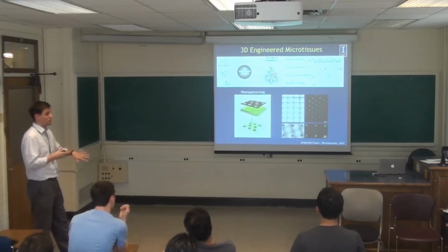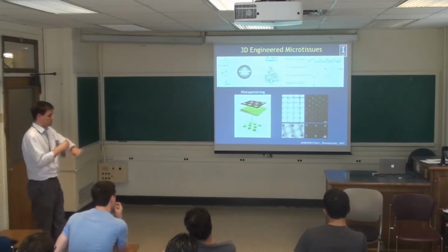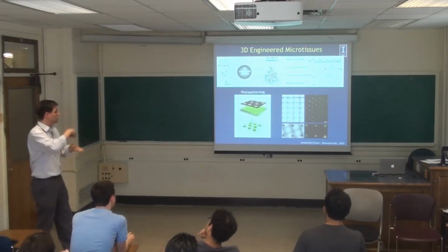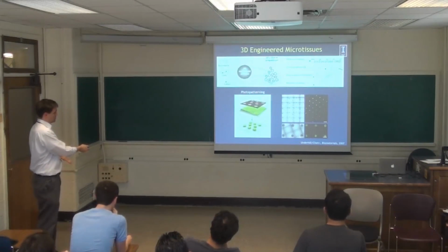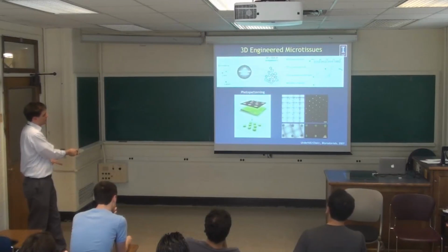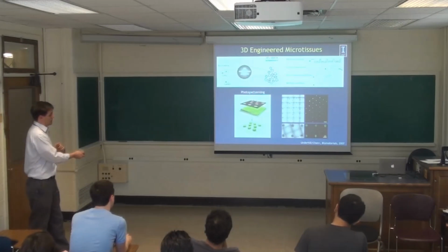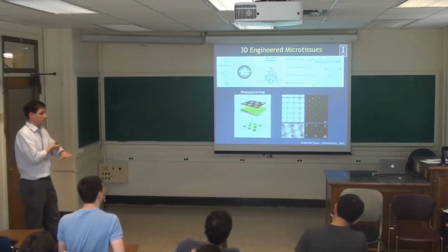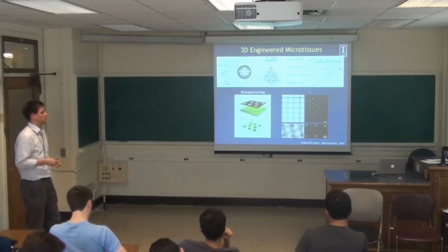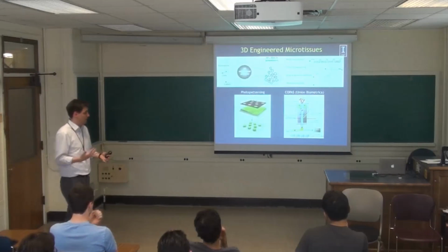One way that we used in some of our initial experiments was essentially photopatterning. So essentially, if you have your pre-polymer solution with cells and then you expose it to UV through a mask, illustrated here, then you essentially will have these microscale domains that polymerize, which is illustrated here. And then for these experiments, we could essentially just release those from the surface, and then you have hundreds or thousands of these miniaturized domains in suspension. So then how could you analyze this?